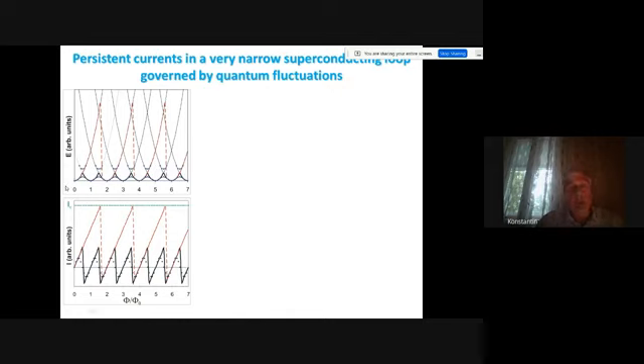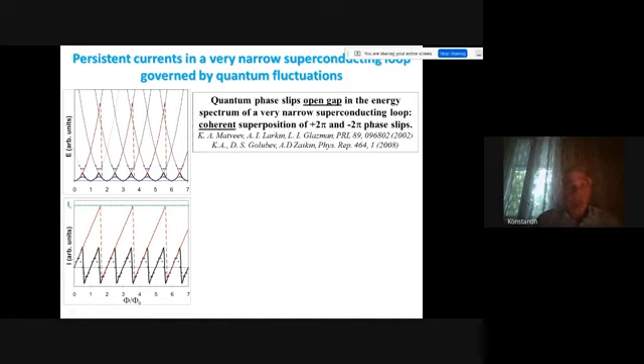However, if the system always goes along the ground state, then it will be a sawtooth behavior strictly with one fluxon periodicity. The question is, when will the system finally go from one quantum state to another one? The answer is given on the second plot. When the current, which is the derivative of energy by flux, is equal to the critical current, then the current circulating in the loop will be big enough to suppress superconductivity and the system goes to the ground state. So that was about a macroscopic loop without any superconducting fluctuations. Later it was shown that if we now consider that inside our loop the walls are sufficiently narrow and quantum fluctuations do exist, then a gap opens in the energy dependence.